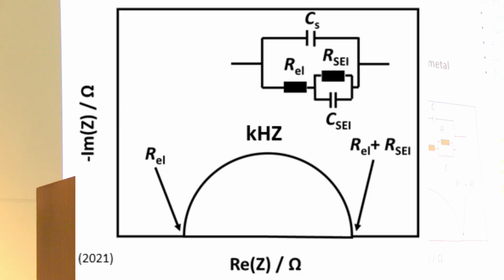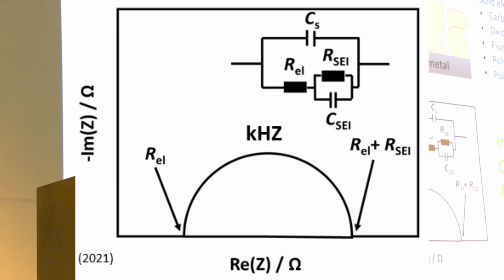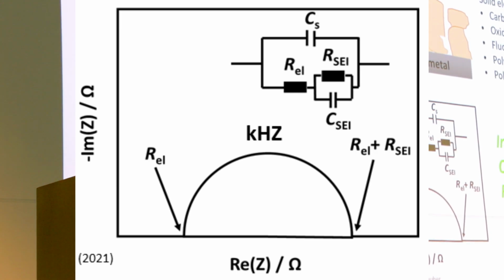Okay, so how can we think about the SEI growth on these metal anodes? I personally can imagine two different mechanisms. One would be that we have either a native oxide layer film, or some kind of initial passivation film on top of the metal electrodes. And this film contains either some electronic conductivity or reactive radicals, and then we have a growth of an SEI from the solid-solid interface.